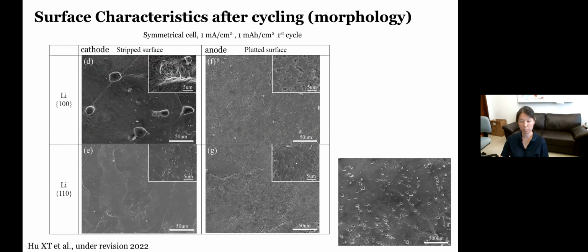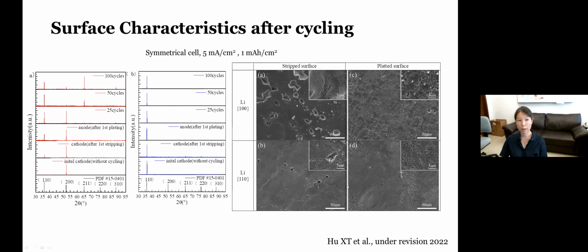Both of them have some plated lithium, and you may argue this one is slightly denser than this one, but I would say the difference is infinitesimal. Now, the pitting also happened on the pristine lithium foils, and here's one of the images shown. Similar phenomena were observed if we cycle the symmetrical cells at higher current densities of 5 milliampere per centimeter square, although the evolution is just faster.